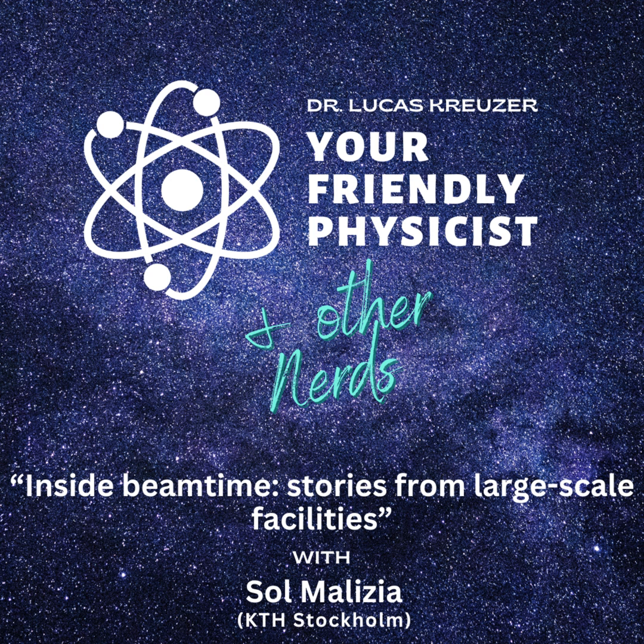Do neutrons damage the samples? No, they don't. That's a good thing. Yes, that's what we like about neutrons. They don't interact with our sample like X-rays. For example, if we expose my cellulose films to X-rays for a long time, they will just burn, they will just carbonize. That doesn't happen with neutrons. We can just measure and measure and measure for hours, and nothing happens. Neutrons are very gentle to your samples. They don't damage anything.